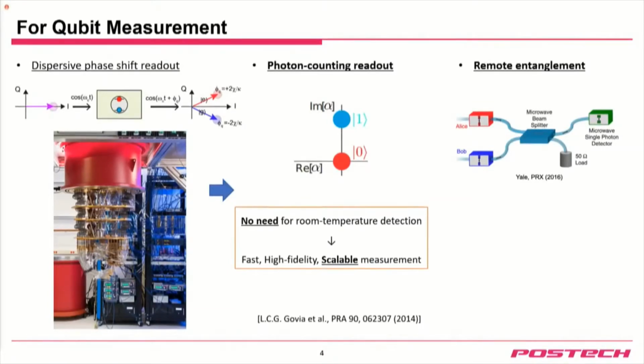Currently, as far as I know, people have been using so-called dispersive measurement, where people inject a reference tone of microwave near the qubit, and depending on the qubit state, this reference tone will have some phase shift. So by measuring this reference signal at room temperature and looking for any shift in the phase, we can infer the state of the qubit. For that, we need to inject the microwave inside the fridge and get the microwave back out to room temperature by amplifying it. So we need a lot of microwave lines and amplifiers, and it will be a lot of cost and overhead for measuring the qubit.